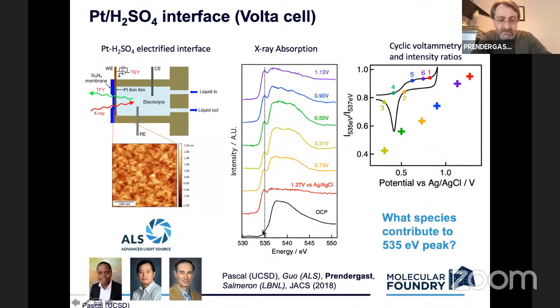And we saw some definite voltage dependence. So on the right-hand side here, in the inset, you can see the cyclic voltammetry data, the numbering system, and the colors correspond to the spectra that were measured. And then in the larger inset figure, what you have here is the ratio of this first peak, indicated by the vertical line here at 535 eV, to the intensity of, let's say, a second peak that begins at about 537 eV. And you see this almost linear relationship between the relative intensity of those peaks and the potential, wherever you are on this cyclic voltammogram.